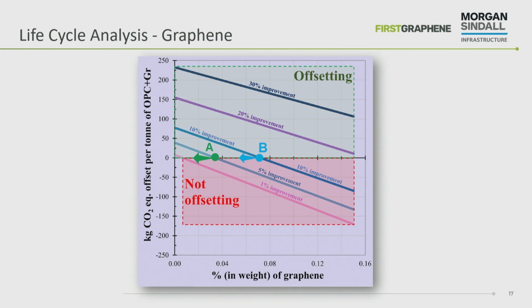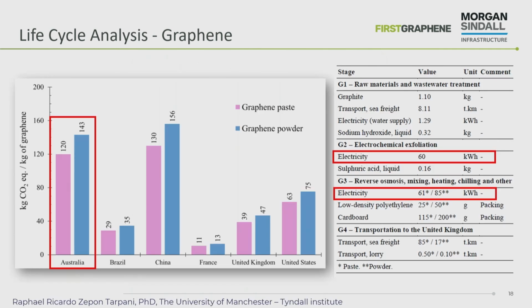These have changed again since the life cycle analysis was carried out. This is the worst case scenario. If you load 0.04, 0.06% of graphene and you get a 10% improvement, then you can see that you can still save a few tens of kilos of CO2 per ton, but obviously we've moved on since then, and it's a much more efficient process. So we might have to rerun that life cycle analysis with the university to make this chart look a little bit better.